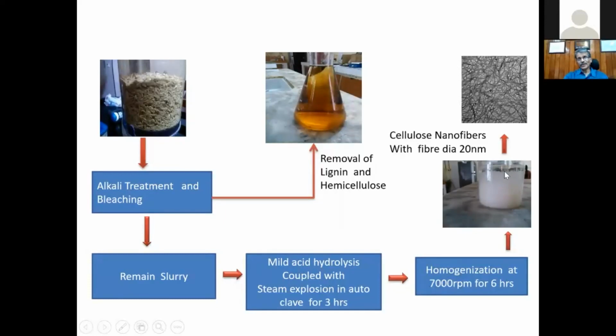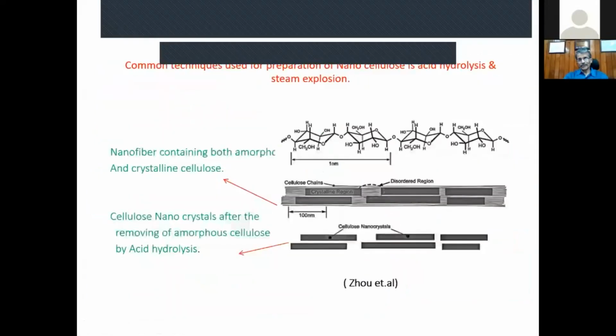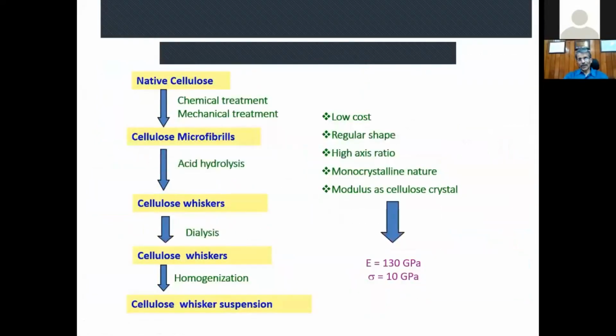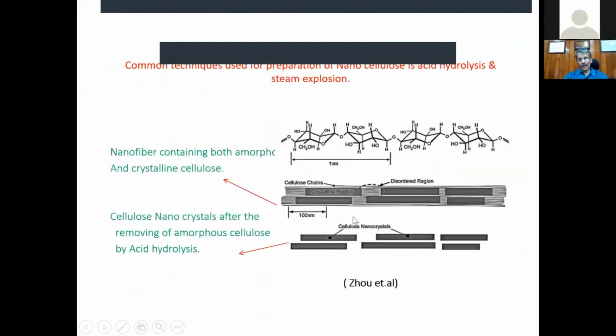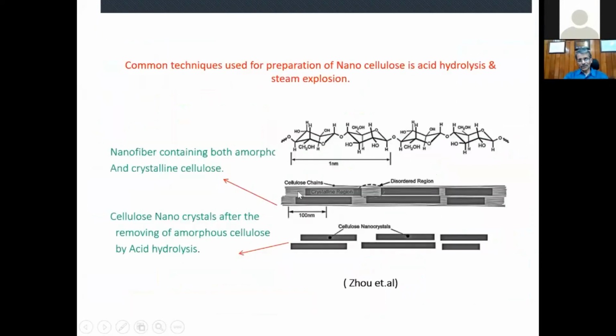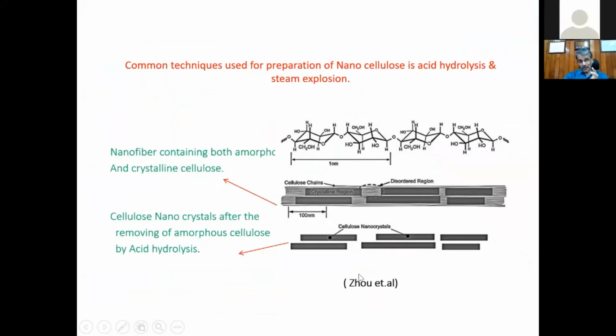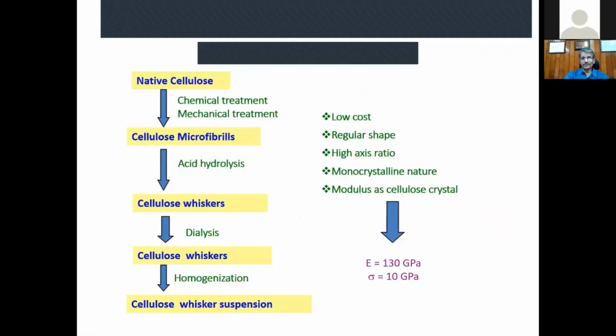Look at the milky liquid. This is nothing but the dispersion of nanocellulose in water. And if you examine it under a high-resolution electron microscope, you see a beautiful structure of nanofibers. Look at the structure of nanocellulose. You have crystalline and amorphous segments coexisting. This is a case of nanocellulose using a light acid. If you use a strong acid, you get short nanocrystals where you remove all the amorphous phase.